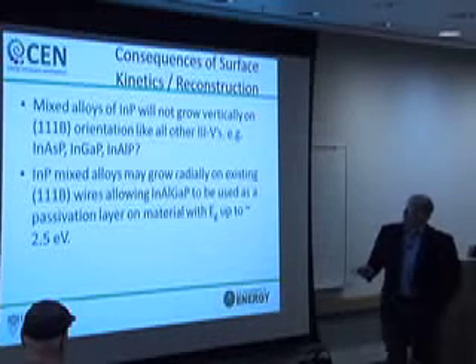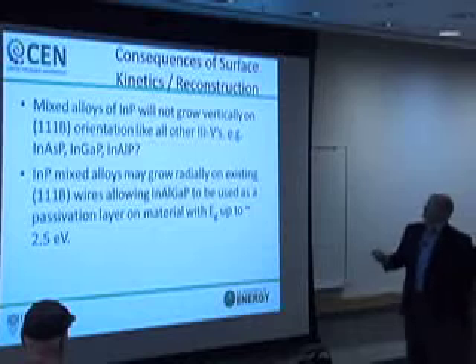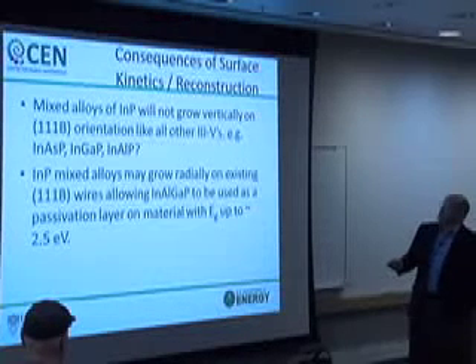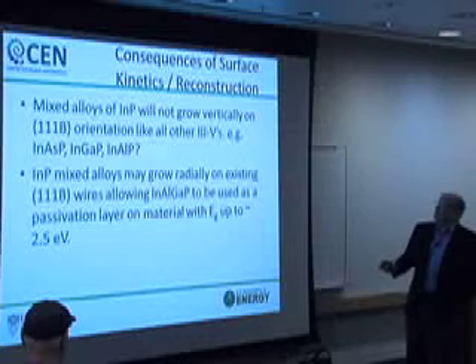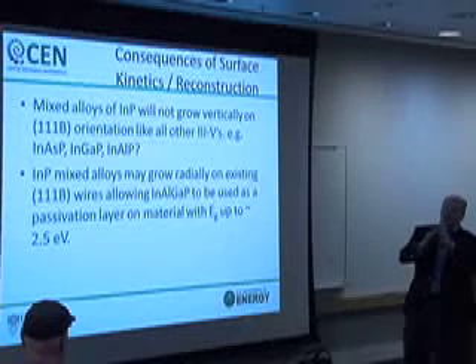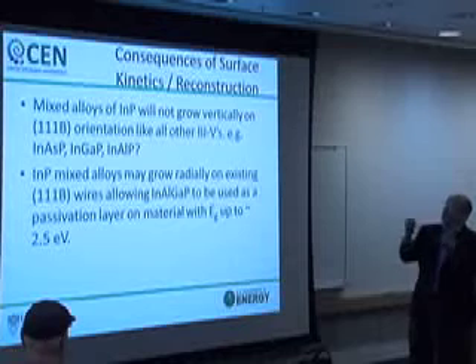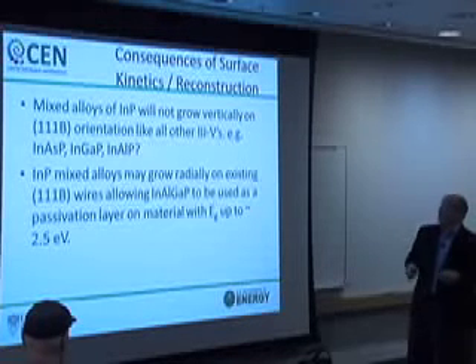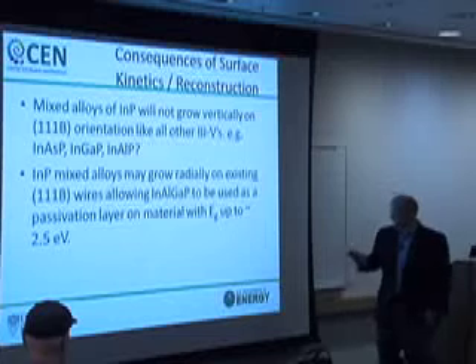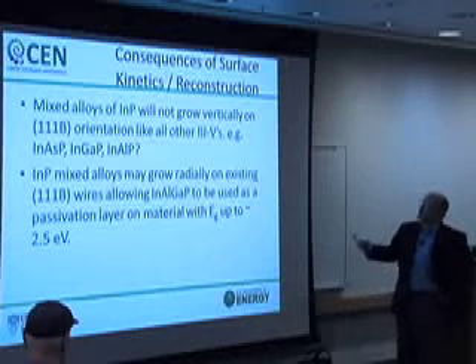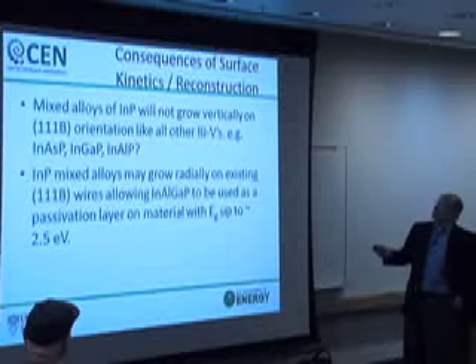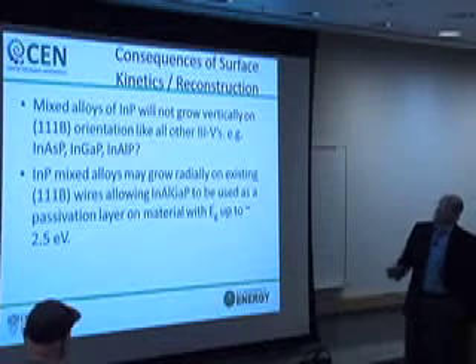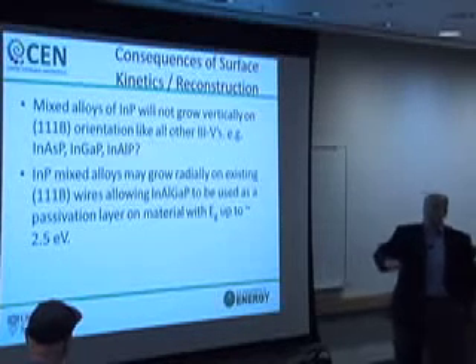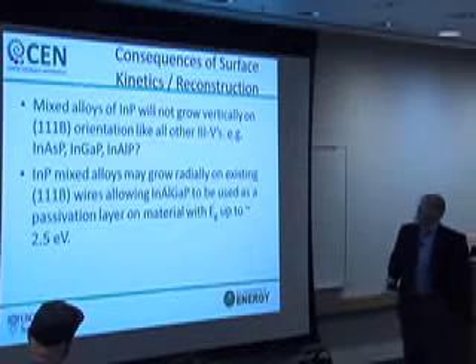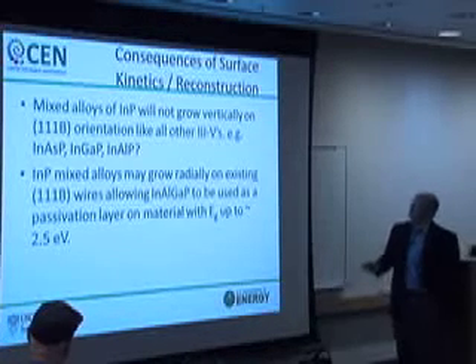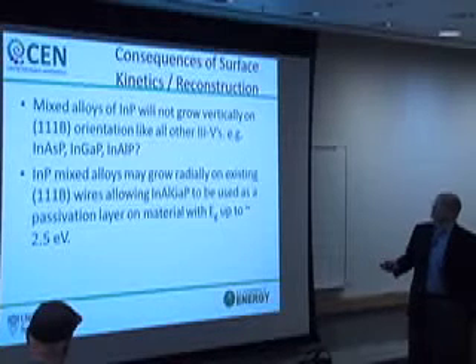So the consequence of that is that mixed alloys of indium phosphide won't grow vertically on that orientation, and indium phosphide mixed alloys then probably will have to be restricted to growing as a radial layer on a core shell kind of structure. I'm not going to touch on this again as we go forward, but this is a case where the surface reconstruction is actually controlling the kind of crystal geometries that you can grow in this field.